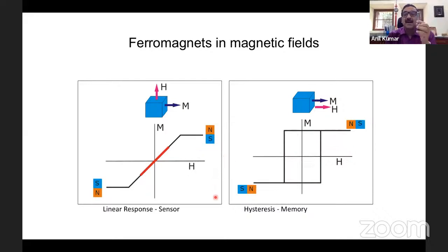And now, instead of applying the magnetic field along the easy axis, if I start applying the magnetic field along the hard axis, what happens? At zero magnetic field, all the magnetic moments are in this direction, so there's no component of magnetization in that direction. But if I start applying a magnetic field, the magnetic moments start aligning in the direction of the applied magnetic field. And finally, all the moments get aligned in the direction of the applied magnetic field. Then it gets saturated. So this saturation and this saturation value will be, in terms of magnitude, the same.